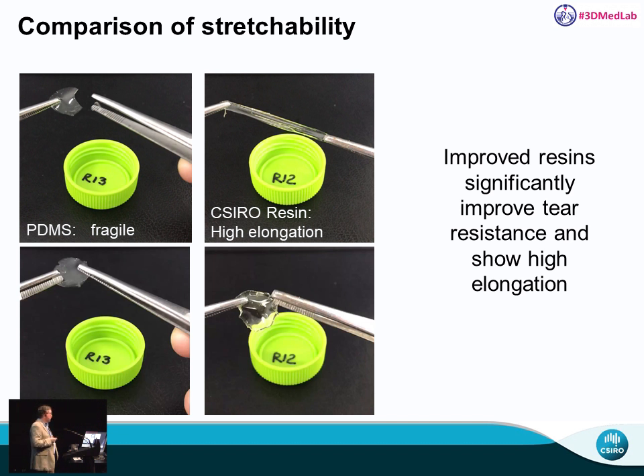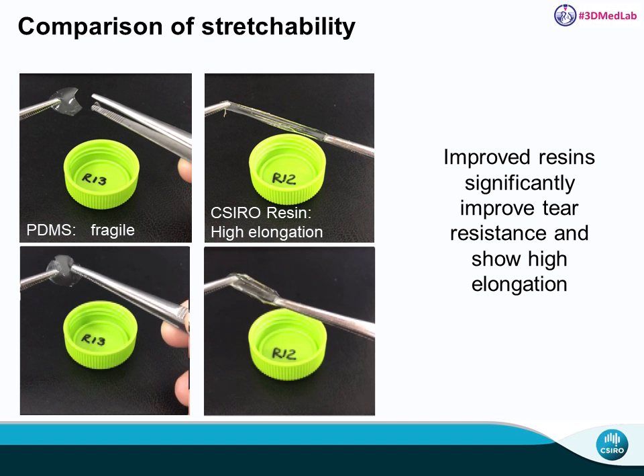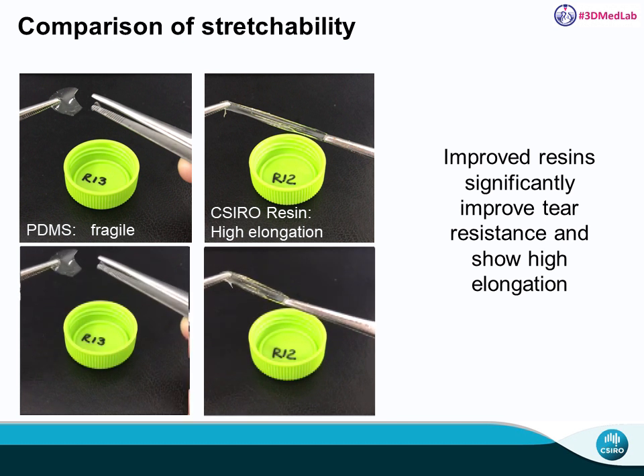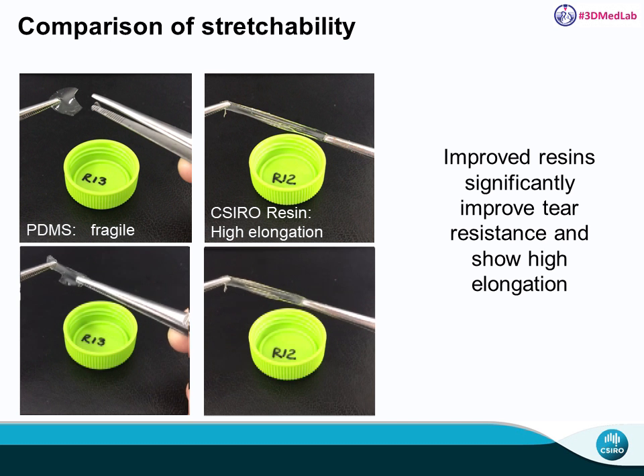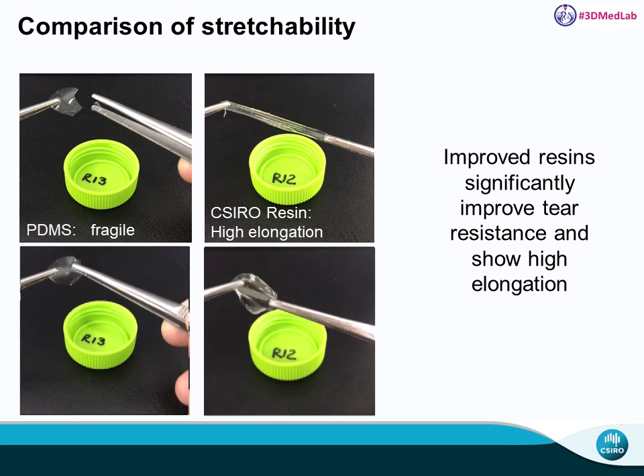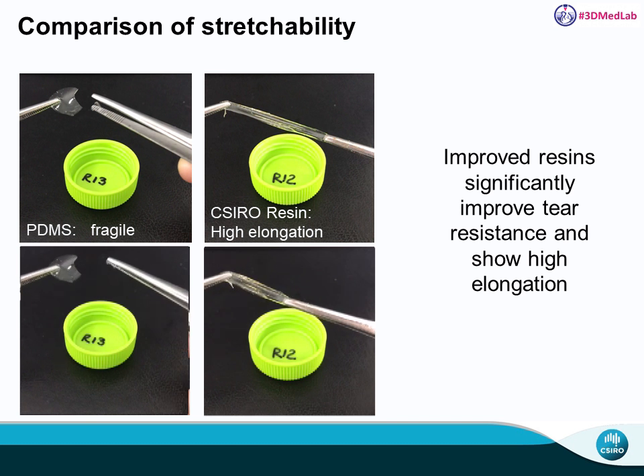We have a range of mechanical properties, I think from around 20 to 60 Shore hardness. We can sterilise them, and they're non-cytotoxic by cell growth inhibition assay, both with and without medium, with and without serum. So part of the problems with the earlier generations were that they were a bit brittle, and when you stretched them, they tended to rip rather than stretch. So we developed some improved formulations which have much higher elongation. So this can be stretched over 100% without breaking. Eventually it slips out of the tweezers.